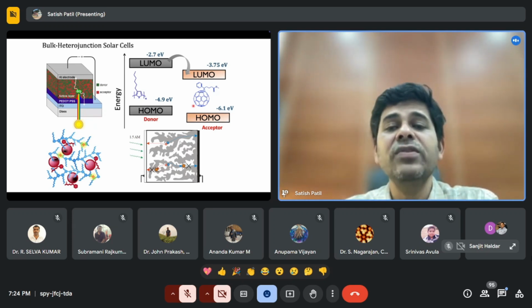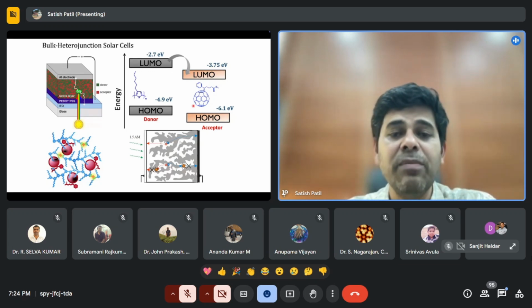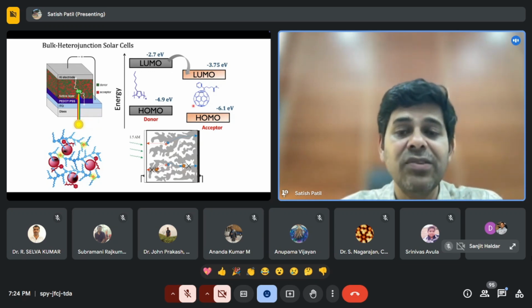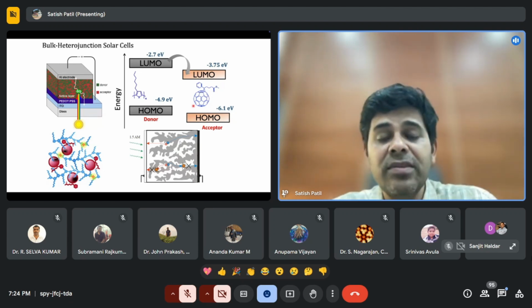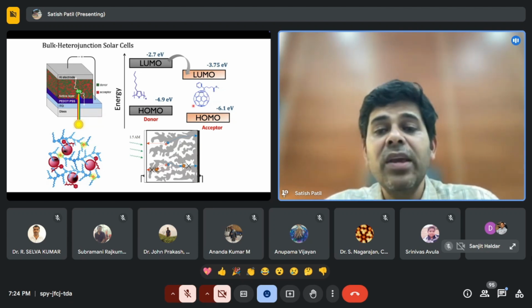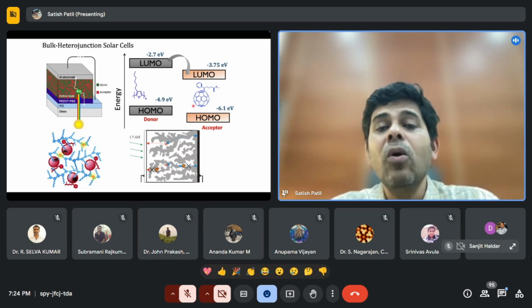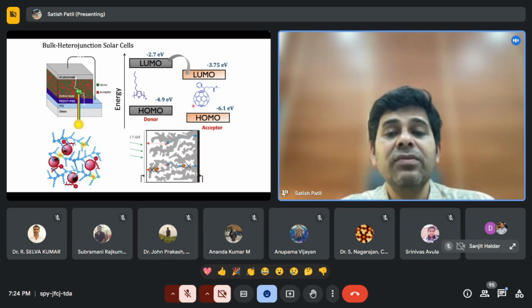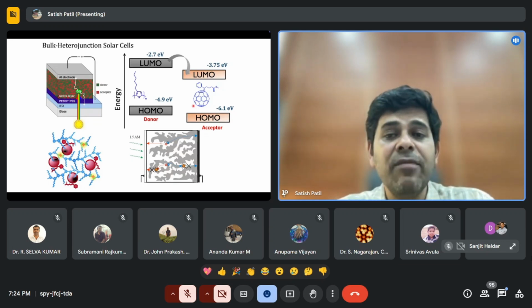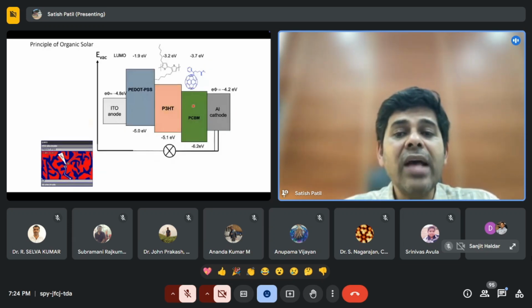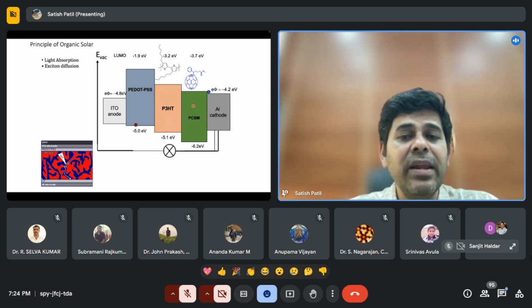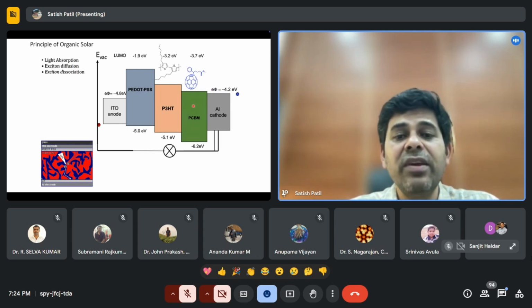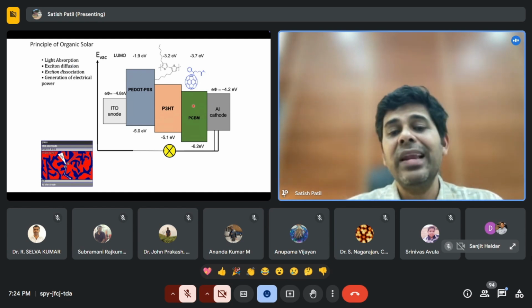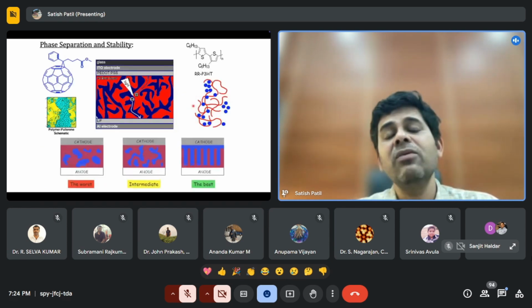You see the Kodak approach was 1%. Now, as of today, people are making more than 20% efficiency solar cells. This is a tremendous transition for solar cells based on organic. So all the difficulties and limitations, the first result by Kodak was 1%. Then as of today, you see this is the animation. Now you shine the light for absorption, you separate the hole and electron by using this kind of a layer and collect them. And this is the way you dissociate excitons and generate the electrical power. And this is where I think you can make it.